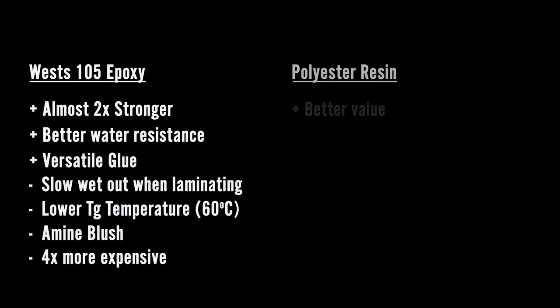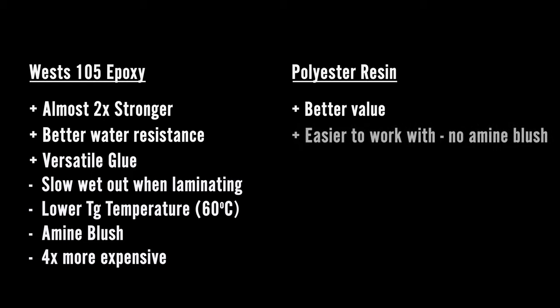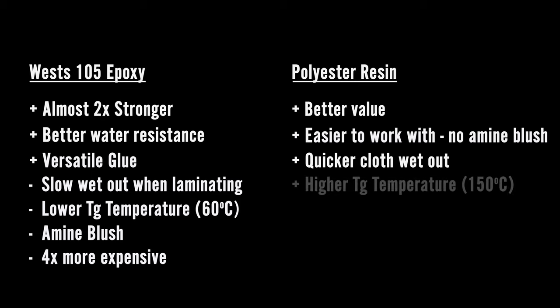One of the most significant disadvantages of epoxy is, of course, just how expensive it is. On the other hand, polyester resin represents brilliant value for money. It is easier to work with. There's no amine blush to worry about. It's not as sensitive to temperature for its cure time. And you can come along the next day and lay up on top of something you did, knowing that you'll get a good bond. General purpose resin is a laminating resin, so you get a nice, quick cloth wet out.